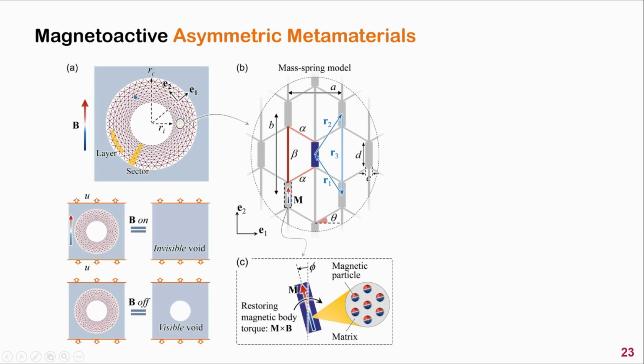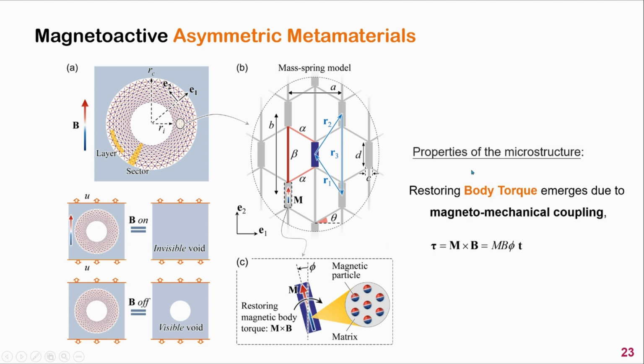Okay, let's consider that the cloak media is made of the mass spring model shown here. Here, the rectangles are the mass blocks made of hard magnetic materials, and the bars connecting the mass blocks represent linear springs. The mass core has the remnant magnetization M, and let's consider that an external magnetic field is applied in the same direction as the magnetization direction. Then, when the lattice is deformed and the mass core rotates under an external mechanical loading, restoring body torque will act on the mass core. Such body torque is what we need to break the symmetry.